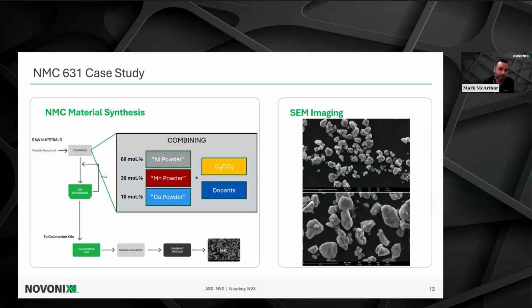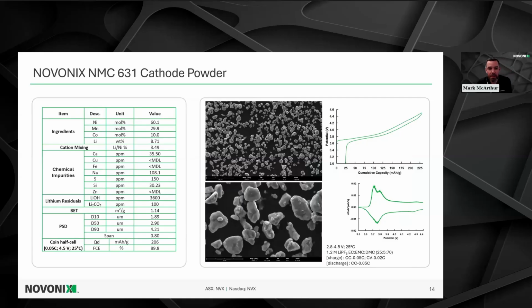The resultant material is shown in the SEM images on the right-hand side of the screen, these beautiful single crystal particles. So there is a lot of data on this slide. I don't want to dwell too long, but if you do look at the left-hand side of the slide, you do see a table of numbers. For those who know what makes good physical properties for an NMC material, you'll start to see some of these numbers make a lot of sense, and they're comparable to commercially available NMC 631 style powders. And the right-hand side of the slide illustrates just simple voltage curves and differential capacity from coin half-cell measurements made on this NMC 631 cathode powder.